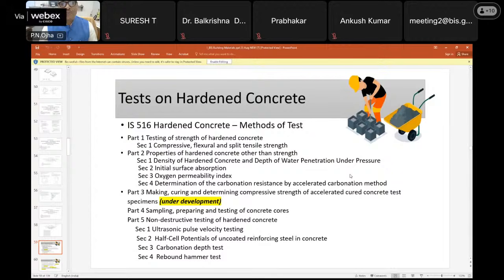So these are the set of tests. One is testing the strength of hardened concrete, and these tests are compressive strength, flexural strength, and split tensile strength. Then other properties like density of hardened concrete, then depth of water penetration test, and initial surface absorption test. This is one of the durability indicators. The earlier one, the water penetration test, is also a durability indicator. Oxygen permeability index is also a durability indicator test. Then determination of carbonation resistance. Carbonation is one of the problems of concrete from the durability point of view. Okay, so the carbonation resistance test.